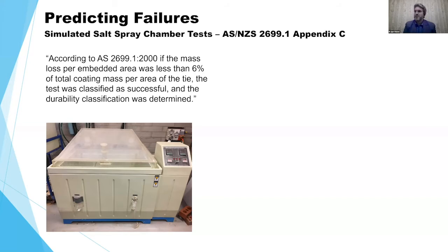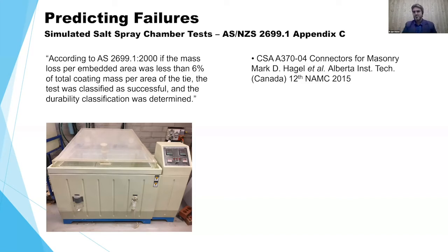Well, there are some smart people before me, and they've done lots of accelerated tests. They've used the AS2699 from 2000. And it says there that after a certain number of hours in a salt spray, which is artificial seawater exposure during intermittent or continuous spray, there are various ways to do the test. But effectively, after a certain percentage of mass loss has been accumulated or quantified, you consider that the material has failed its service, yeah? So just to give you an idea of what we're looking at. And then we try to predict what happens in real life, yeah? That's what it's for. This is just a generalization from the salt spray test.